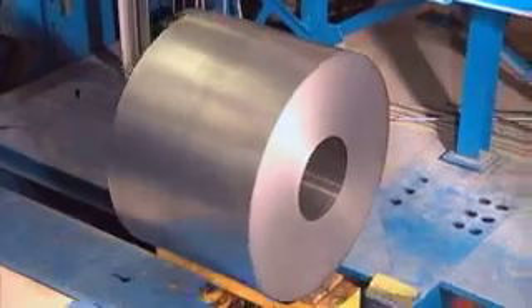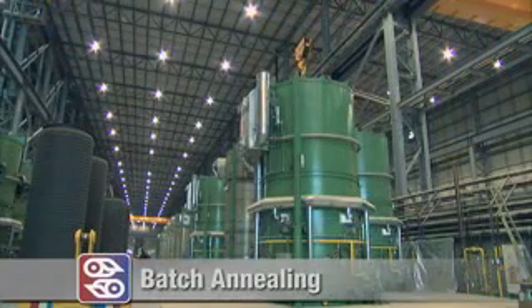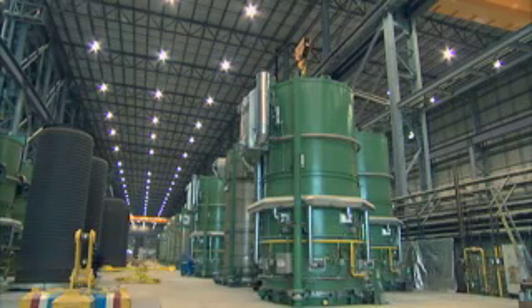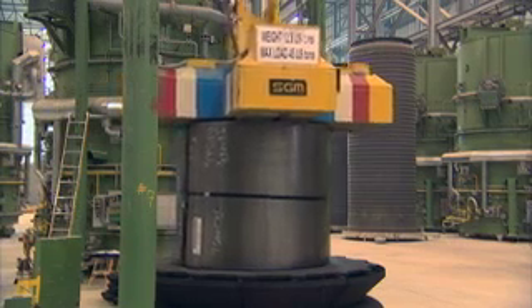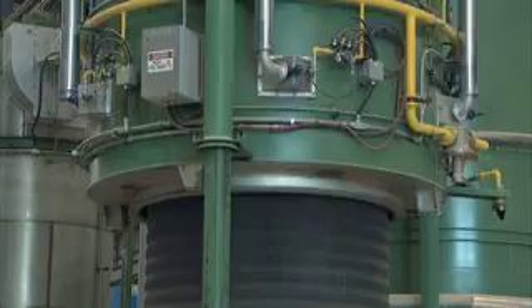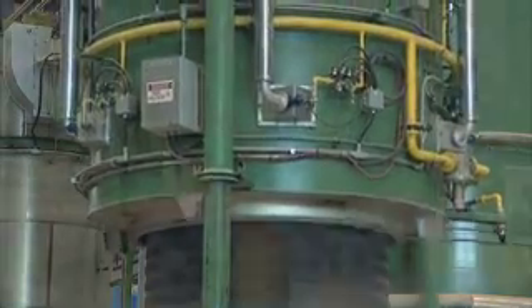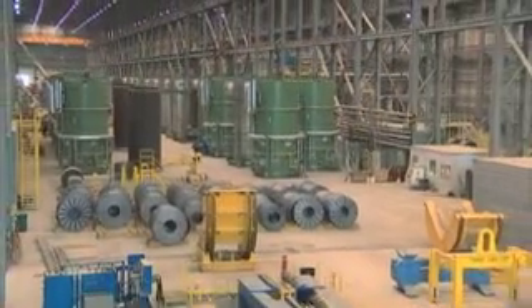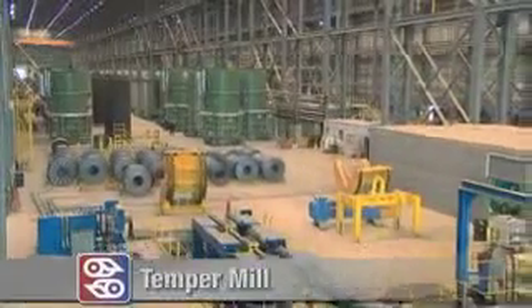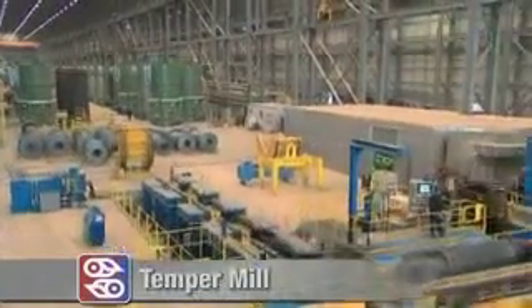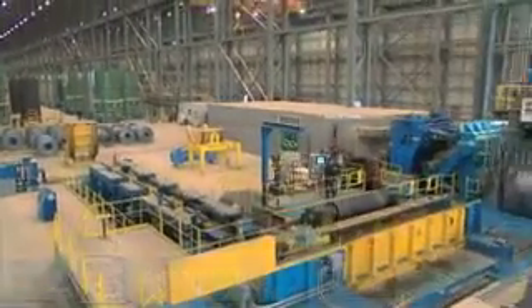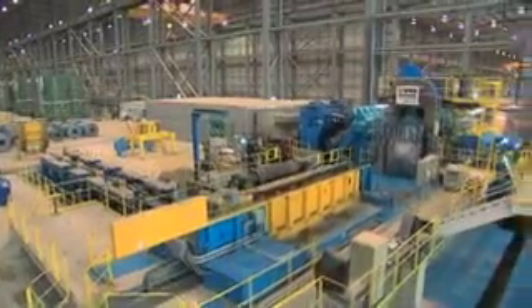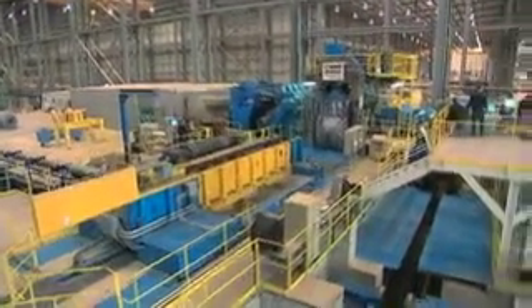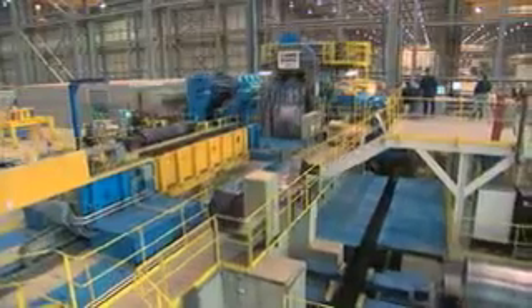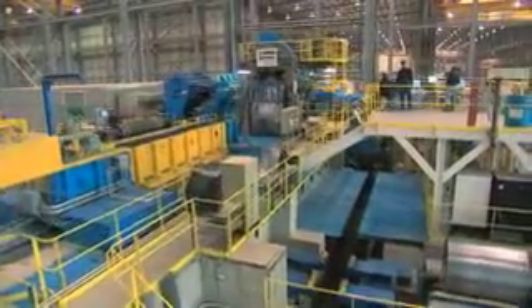Batch annealing, a value-added process for full hard cold roll, restores ductility for improved stamping and forming. Coils are stacked and cooked in hydrogen atmosphere furnaces. After about 3 days in the furnaces, the coil moves to the temper mill, where the customer's specifications for surface finish and mechanical properties are met. This product is sold as fully processed cold roll and is used in lawn and garden products, appliances, tubing, and shelving.